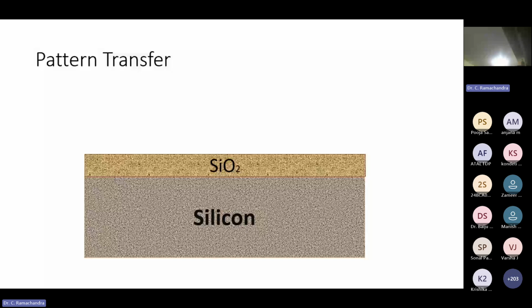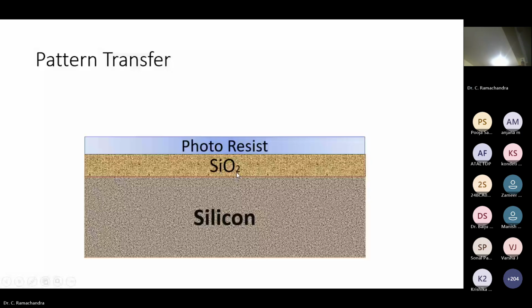Once I deposit silicon dioxide, typically 1 to 2 micron, then I deposit photoresist, which is also typically 1 or 2 micron. So I want to create a pattern, but I cannot directly create. Therefore, I'm depositing silicon dioxide. Then after that, I'm depositing photoresist. Once photoresist is ready, I am exposing through the mask.